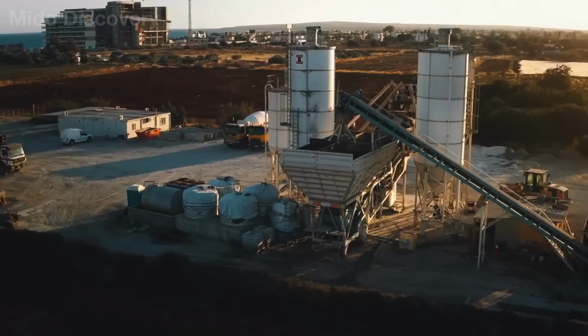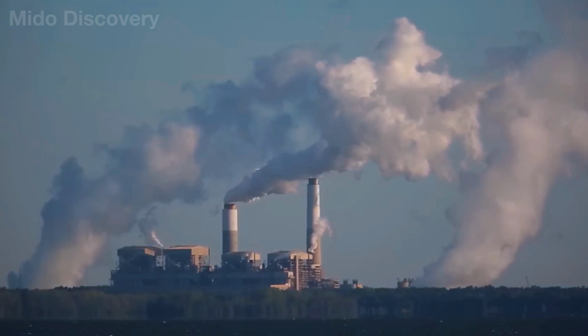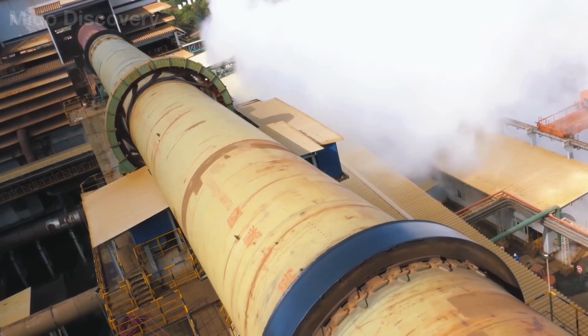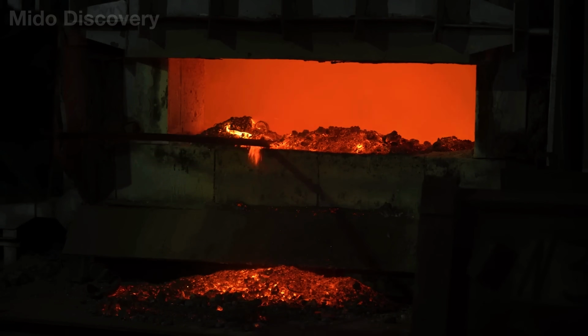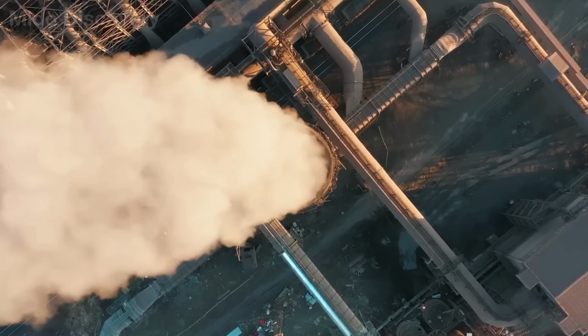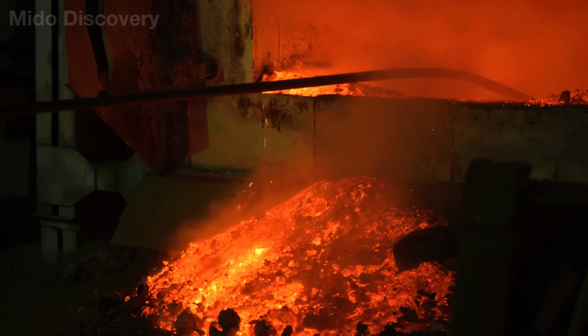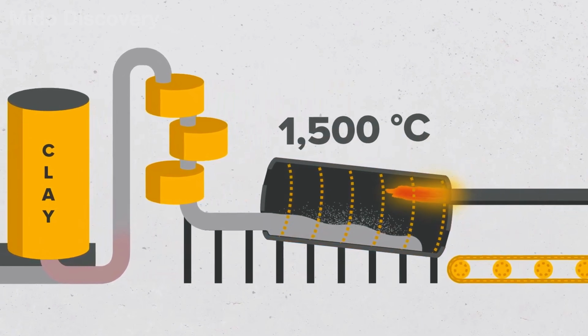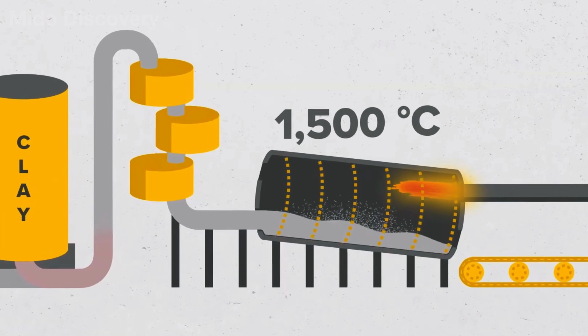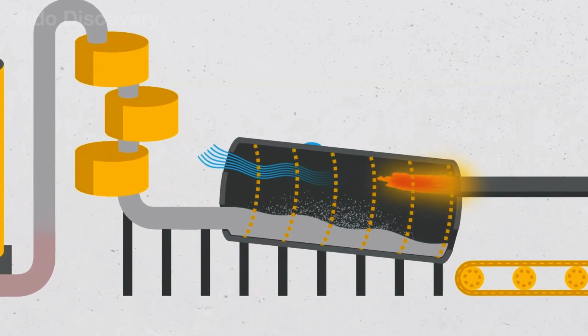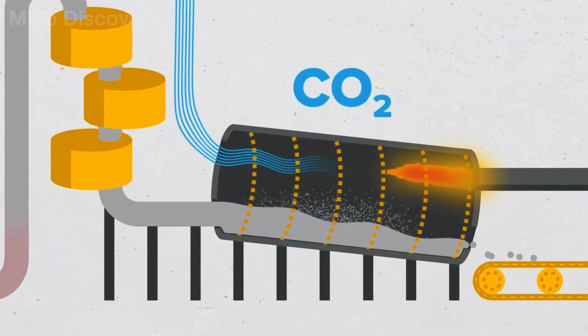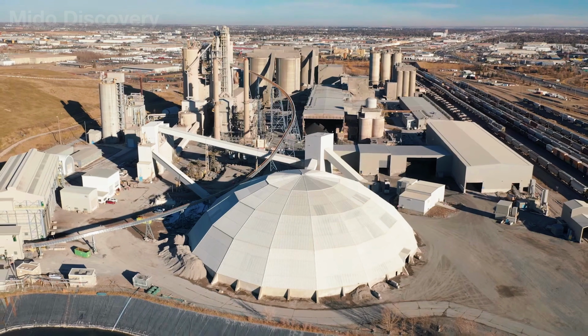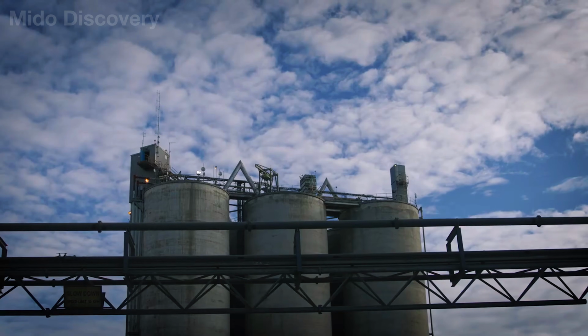Around 60 to 65% of the CO2 released during clinker production comes directly from this reaction, while most of the rest comes from the fuel burned to generate the intense heat required by the process. On average, producing 1 ton of cement generates around 0.6 tons of CO2. That figure has fallen by more than 20% since 1990, partly because manufacturers have gradually reduced the amount of clinker used in cement. But those improvements have still not been enough to offset the continued growth in global production.